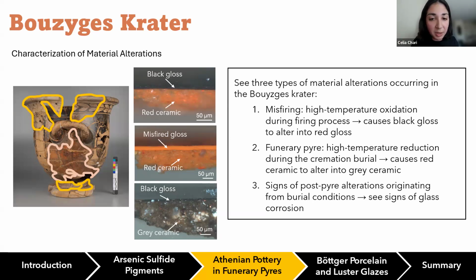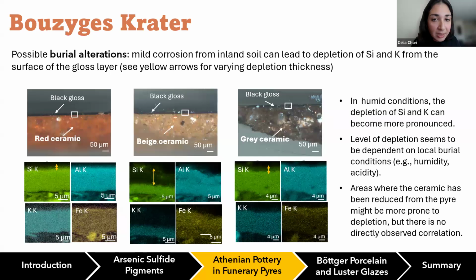I won't go into it with too much detail, but with the burial conditions, so that you have an idea of what I mean, there is a depletion of silicon and potassium at the very surface of these gloss layers. And this could be due to the local humidity or acidity of the soils in which these fragments were buried. So this is not something that is dependent on whether those fragments were misfired or exposed to the pyre. All of the fragments, no matter what condition they had, experience this kind of silicon and potassium depletion. So this is a completely different third alteration mechanism that's occurring. So yes, a little gruesome to think about this crater being used in a funerary pyre, but it's really interesting to see that this is a part of the lifetime of that object, and now it is physically a part of the object too.